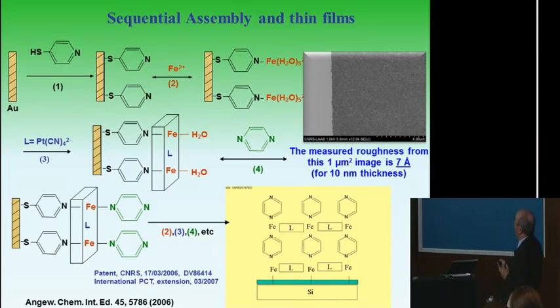What you can see with this technique, we can have very nice thin films, as you can see here by electron microscopy. So then by playing with all the parameters of the surface deposition, I mean concentration, temperature, etc., you can increase the quality of your surface, we can have even 7 angstrom of roughness, which is sub-nanometric, which is very nice, very interesting. And Lionel will tell you about the chemistry we used in order to increase this.